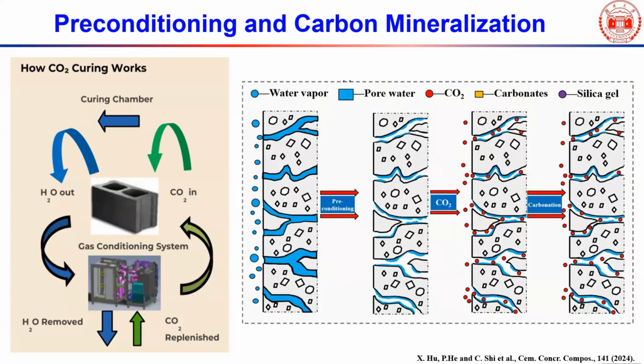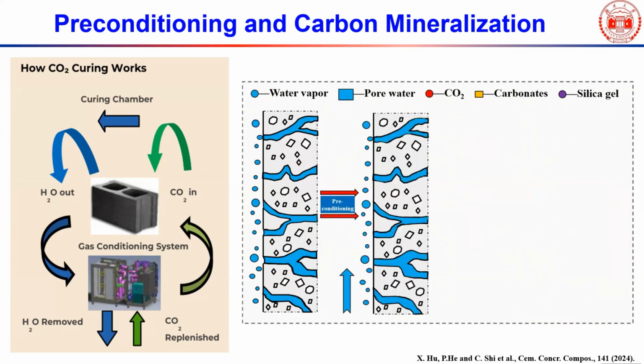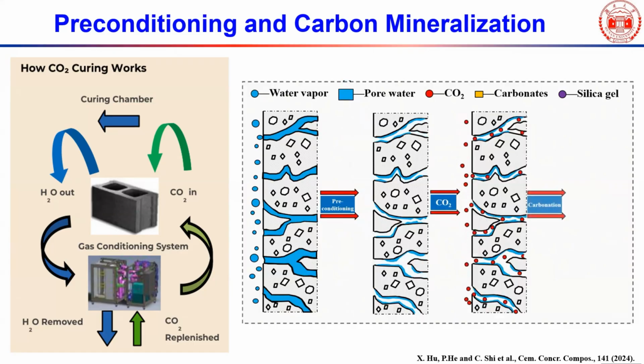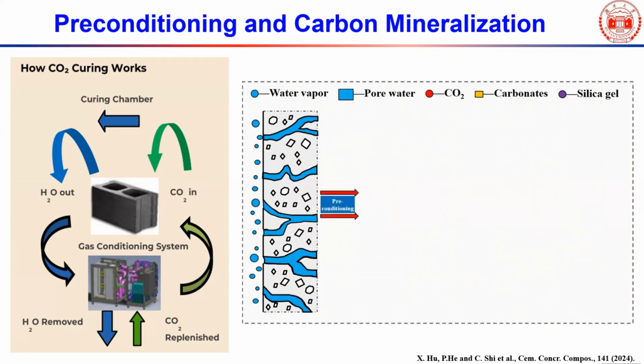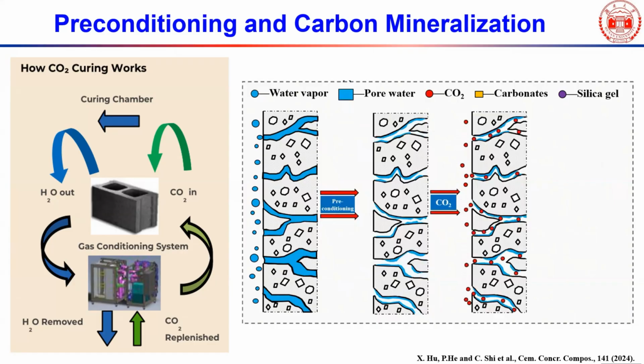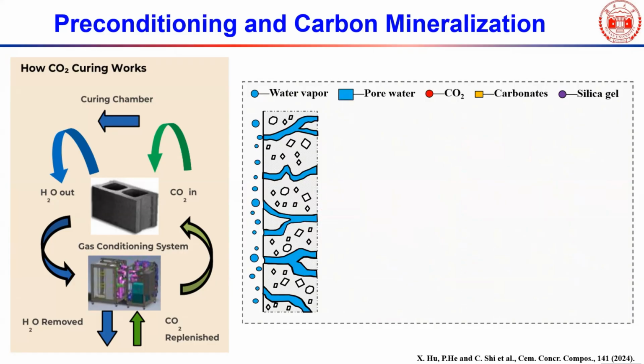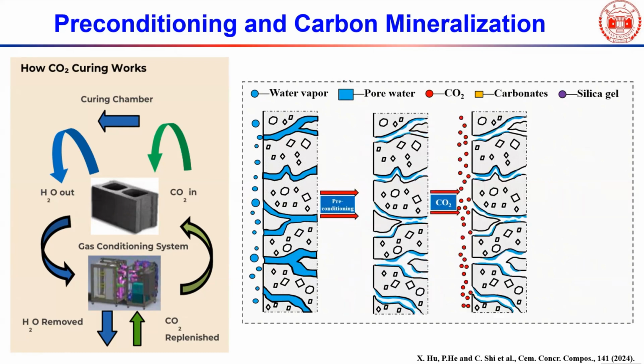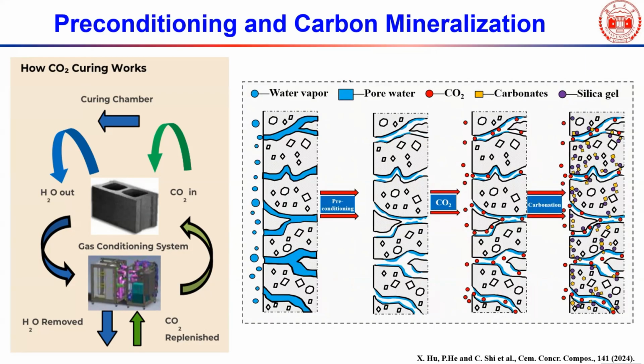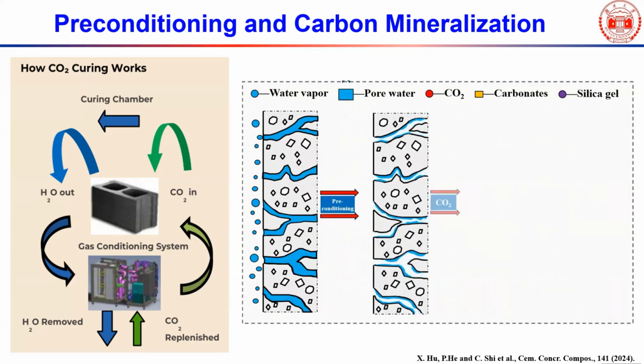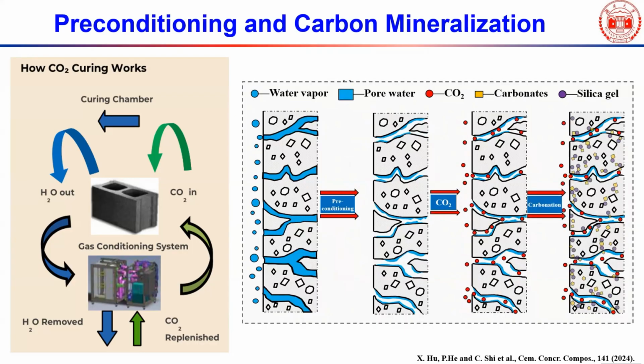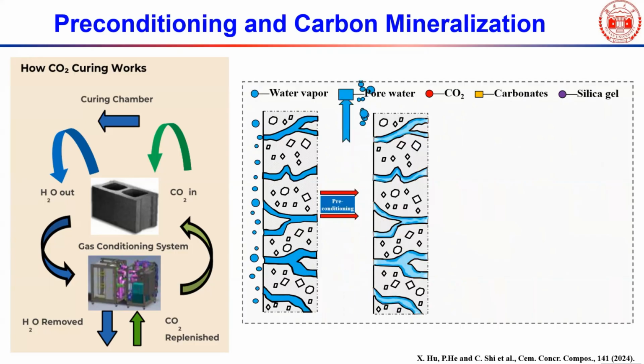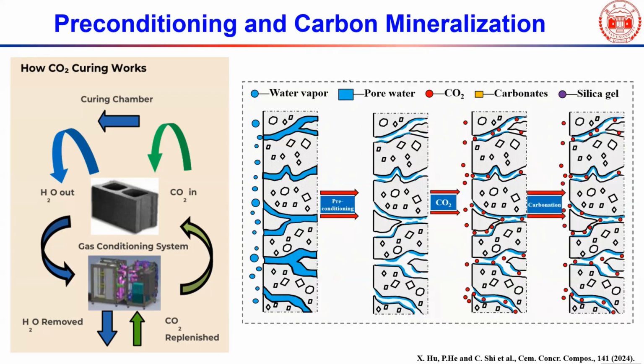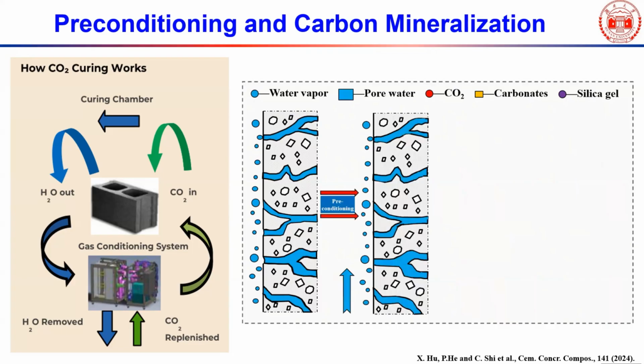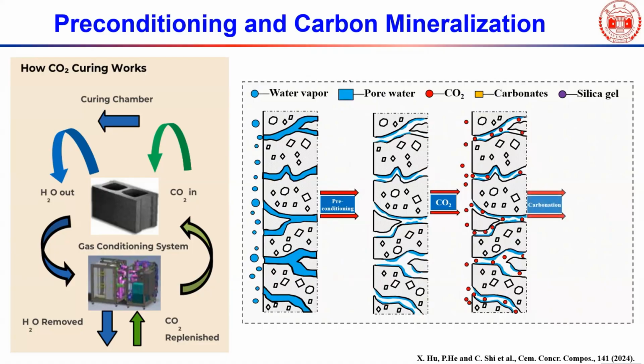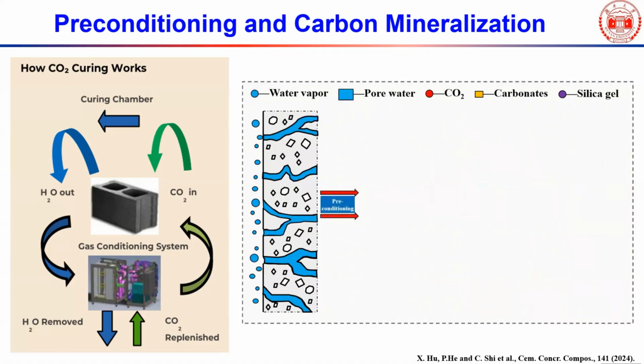Then we developed preconditioning. Initially, we proposed this concept, and then we developed this technology. After molding and casting, we try to remove some moisture and open all these continuous channels, and then inject CO2, so CO2 can go inside those channels very quickly. The left picture is already a flow chart in their marketing flyer document, so basically they use the idea and concept for that process.